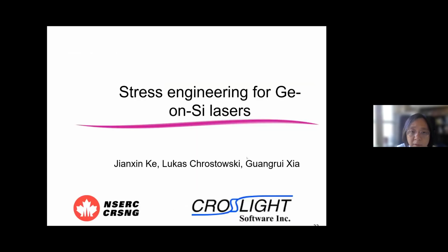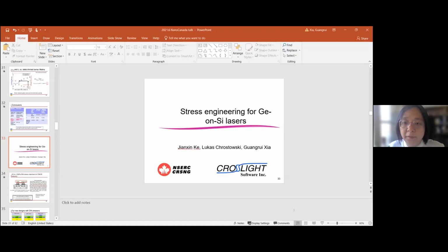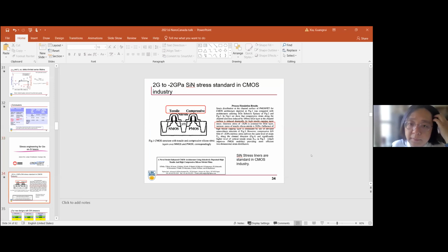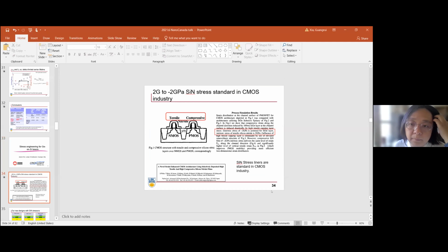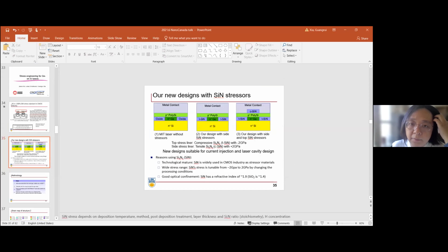Here's another work on stress engineering. So I'll skip all this content. The main idea is that if we add stressors, for example, we use industry widely used silicon nitride stressors to introduce stress on the sides of germanium, for example, here, tensile silicon nitride, and we can also do some compressive stressor.